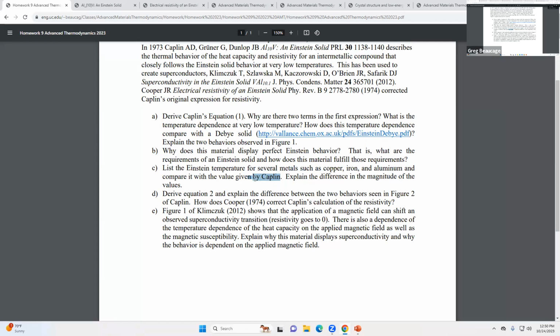We'll go through the various techniques you can use to get these temperatures, the Debye temperature and Einstein. You can get it from spectroscopy, like IR, Raman, and Brillouin scattering, and you can calculate these temperatures from the absorption peaks in those spectra. You can also get these temperatures from measuring the modulus of the material. And then you can get it from a DSC: you can measure the heat capacity with DSC and then calculate the Einstein and the Debye temperature from the measured heat capacity and the thermal expansion coefficient, bulk compressibility.